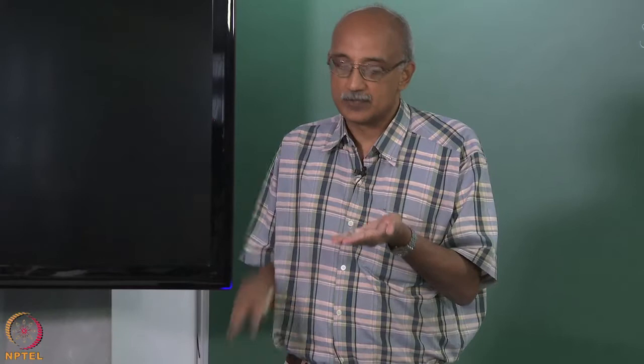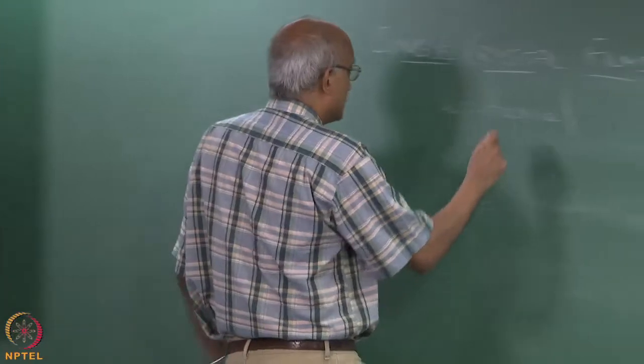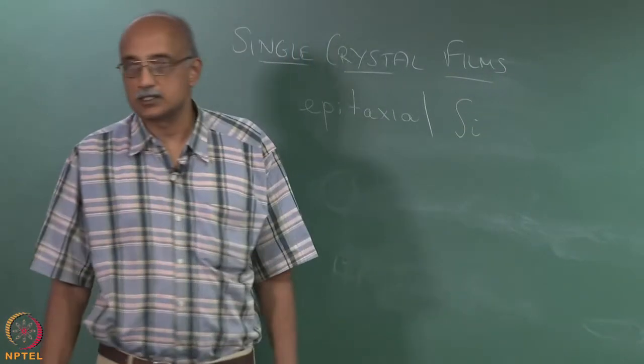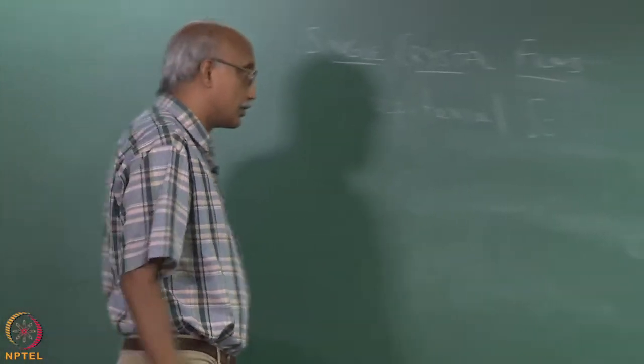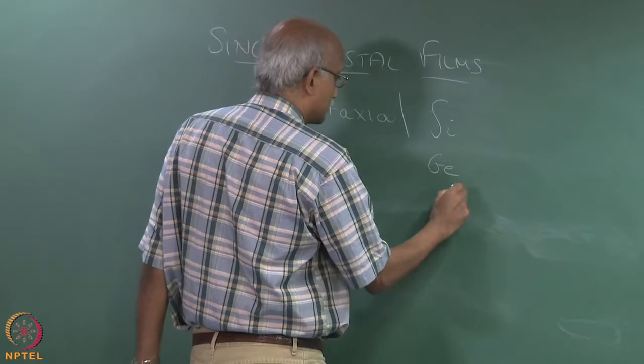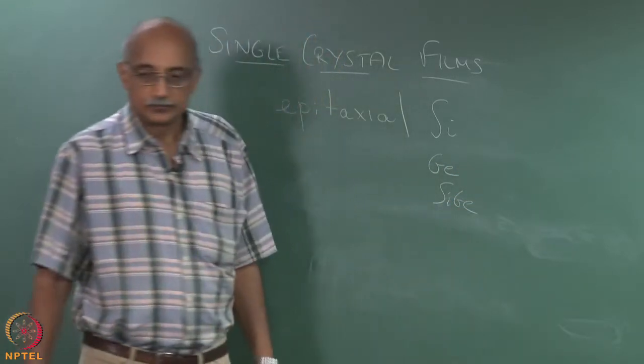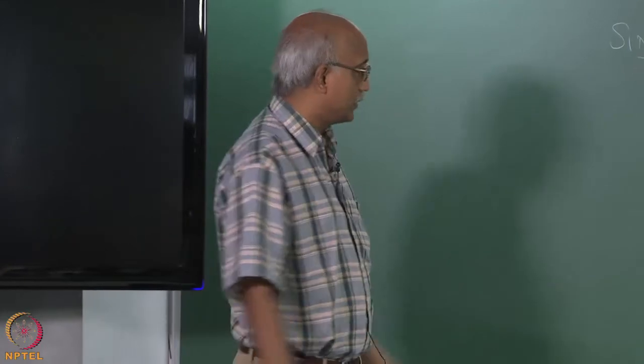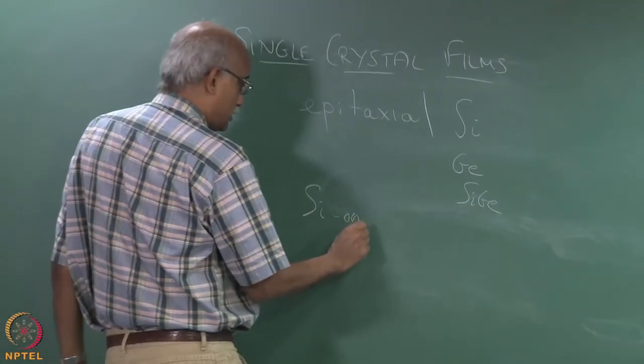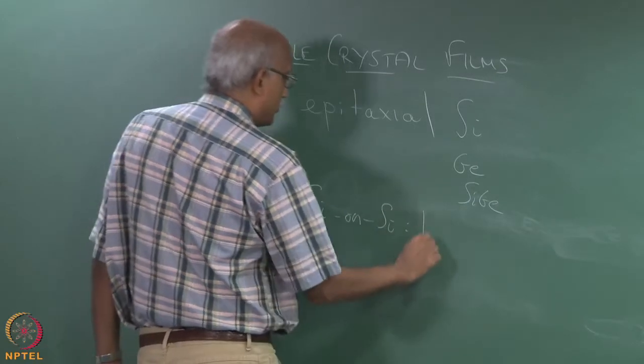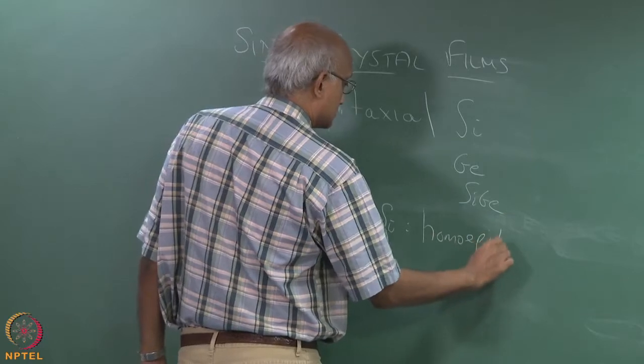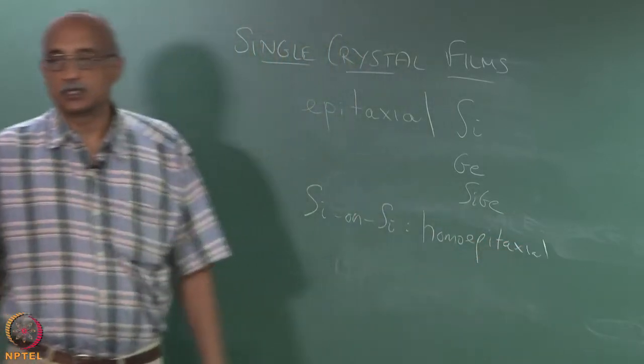In an epitaxial film, you are taking the arriving material and arranging it on the substrate in such a way that you have a very precise crystalline structure at the end of the process. The most commonly realized film using epitaxial CVD is silicon, epitaxial silicon. But others are also used, germanium, even compounds like silicon germanium and so on. The substrate itself can also be of the same material or it can be of a different material. So, for example, when you put silicon on silicon, it's called a homoepitaxial process, where the substrate and the film material are the same.